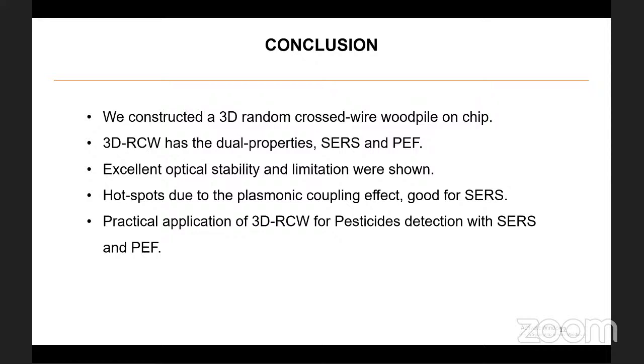In this study, we developed a 3D RCW chip, taking both SERS and PEF effects for detection into account. This chip is stable and provides an excellent limit of detection for R6G. The wood-pile nanostructure present in the 3D RCW chip provides as many plasmonic hotspots, thus leading to higher SERS and PEF response from the probe molecules. And this 3D RCW chip is thus proved to be usable in pesticide detection.